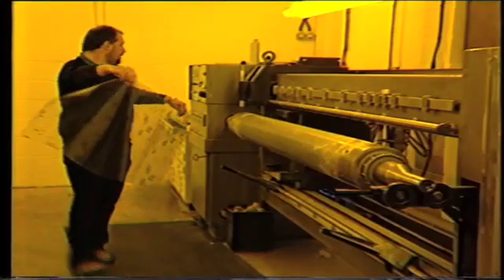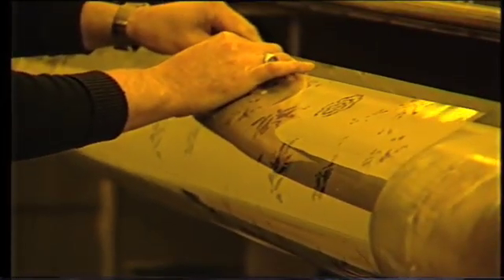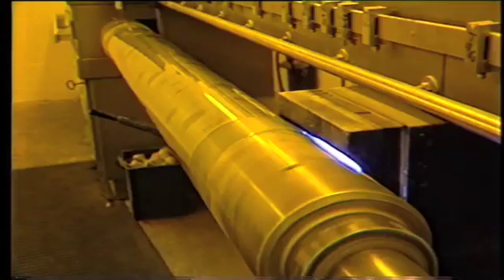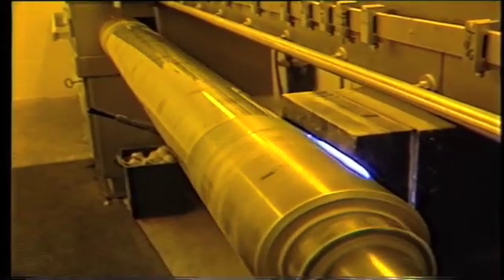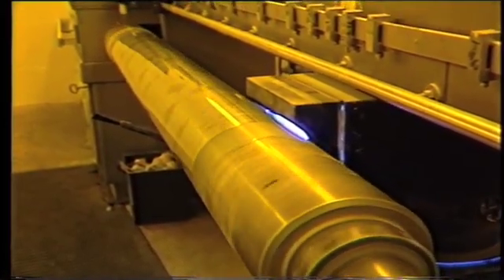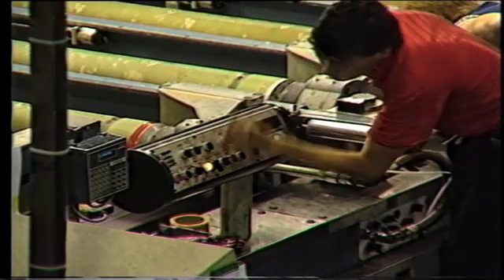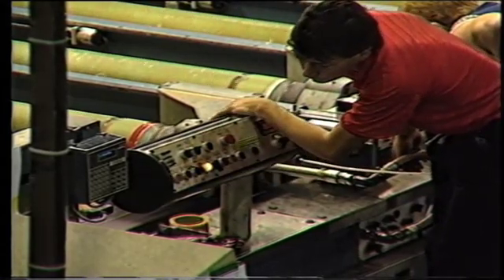At Texplan, a photographic technique engraves the colour-separated films, which show each coloured part of a design, onto the surface of a cylinder. The design areas form holes on the surface of the cylinder, and dye paste is pumped into the middle of each screen and forced out through the holes by a steel blade or magnetic rod onto the fabric as it passes beneath the screen.